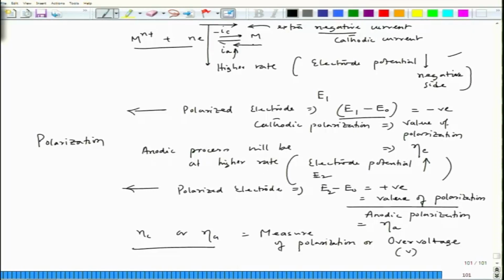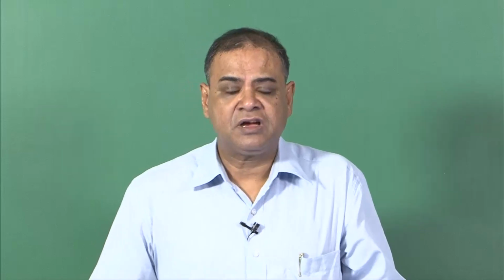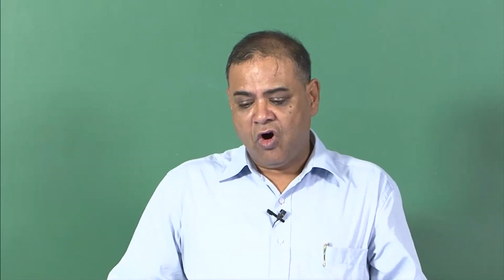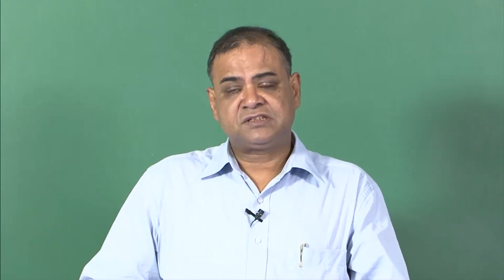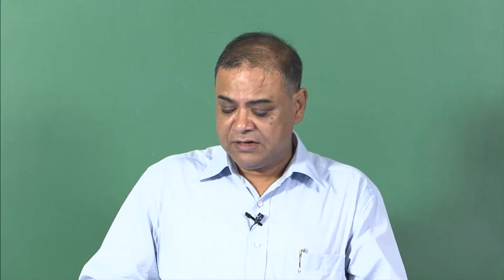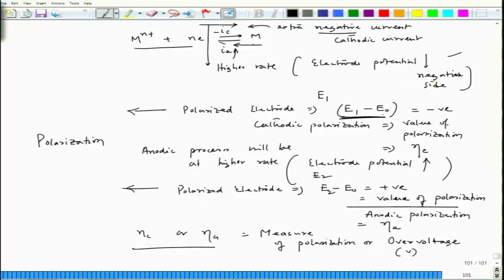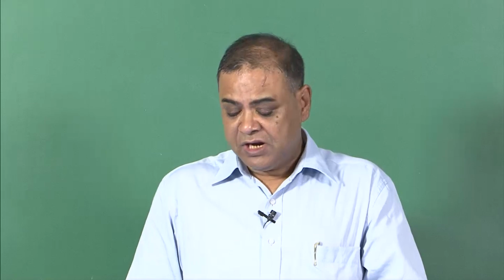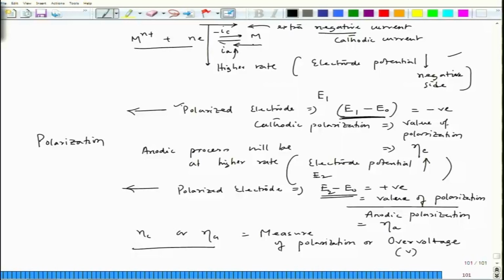From this discussion, what we see is that polarization happens because of the supply of extra current, either on the positive side or negative side, either extra cathodic current or extra anodic current. If we send extra cathodic current, the potential drops from the equilibrium potential, which is E0 here, and when we send extra positive current, or anodic current, the potential increases from the equilibrium potential, which is E0 here also, and the difference in that potential is the measure of polarization. In this case it is cathodic polarization, in this case it is anodic polarization.